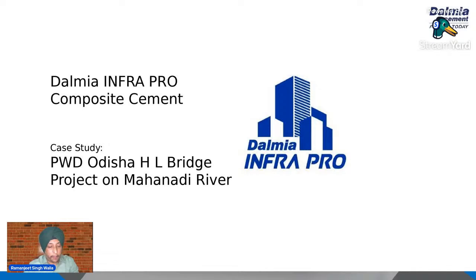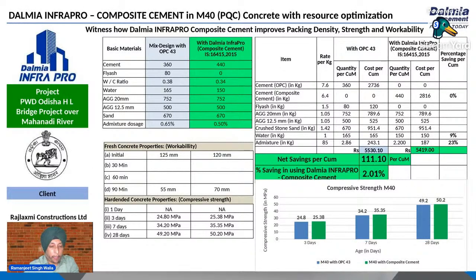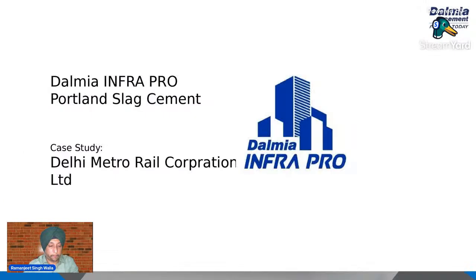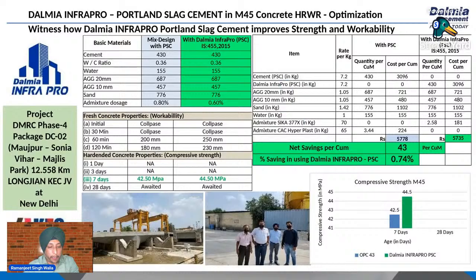This is a bridge, HL bridge in Odisha. Here we are successfully using M40 grade in PQC in 440 kg cement. We are getting 50.2 MPa in 28 days. This is DMRC. In DMRC, we are using 430 kg of our PSC slag cement, and our results are very good. Even in all the projects in DMRC and NCRTC, National Capital Region Transport Corporation, it is being used.